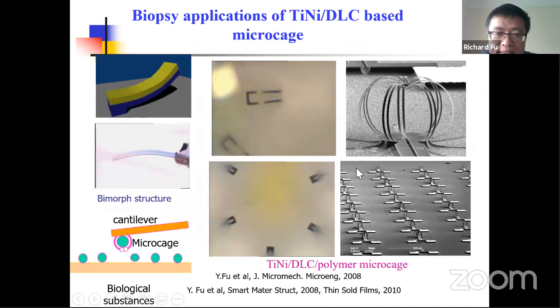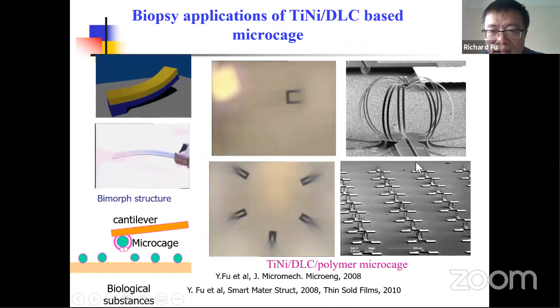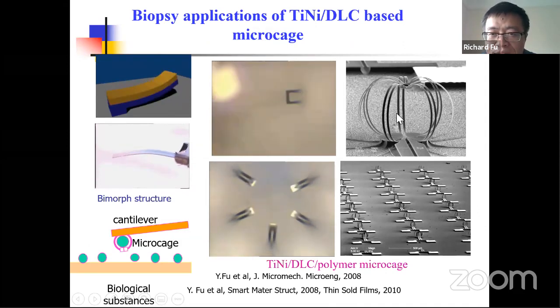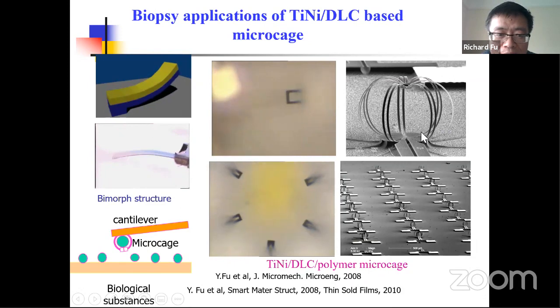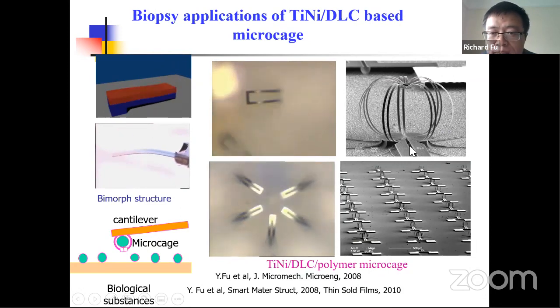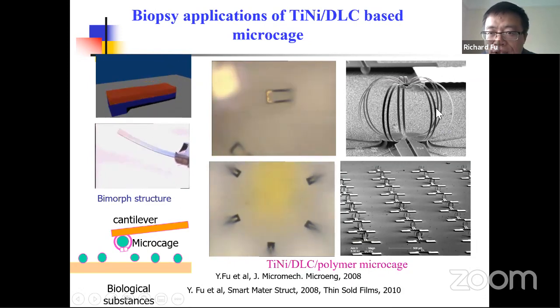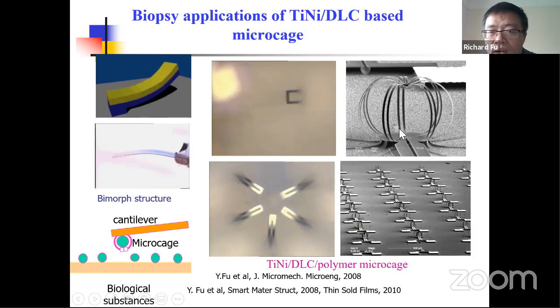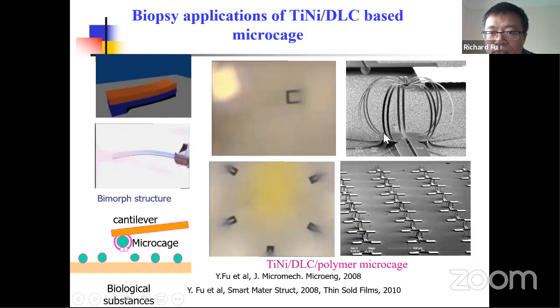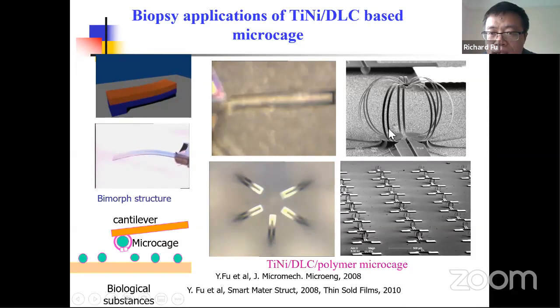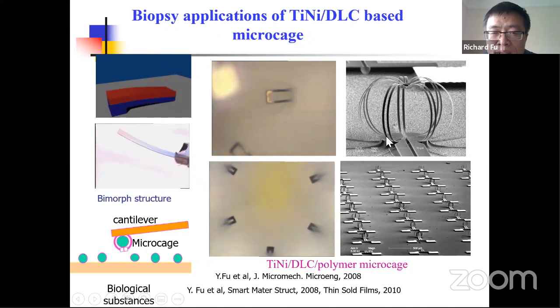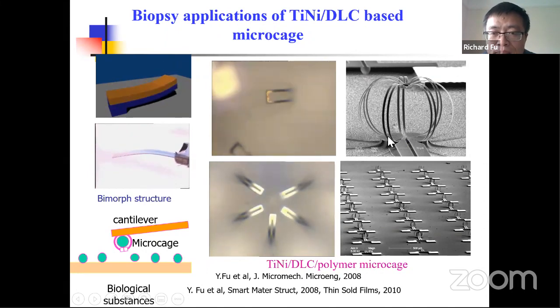So for this application, we were thinking that we can have some other structure, using a few finger structures. We form a kind of cage structure. This cage structure is basically multi-finger, using the two-layer design. In this two-layer design, we use titanium nickel with shape memory on the top layer, and at the bottom we use diamond-like carbon.